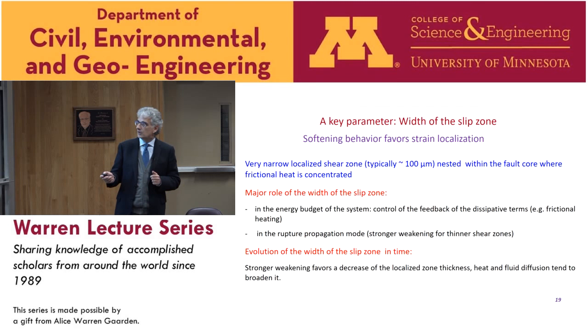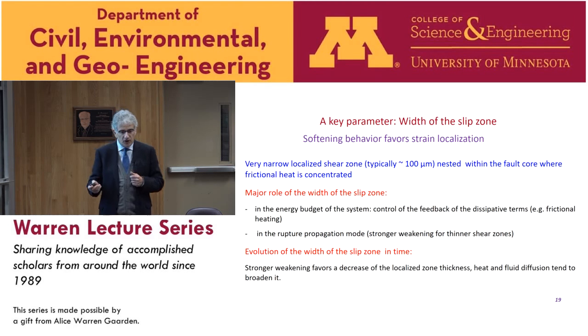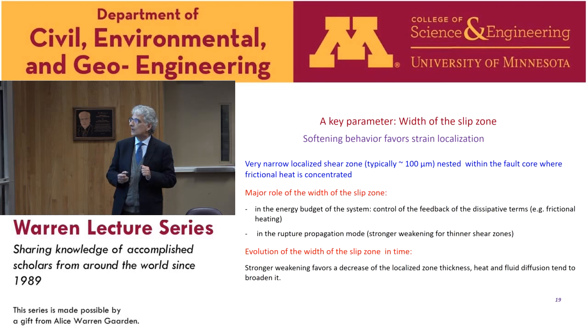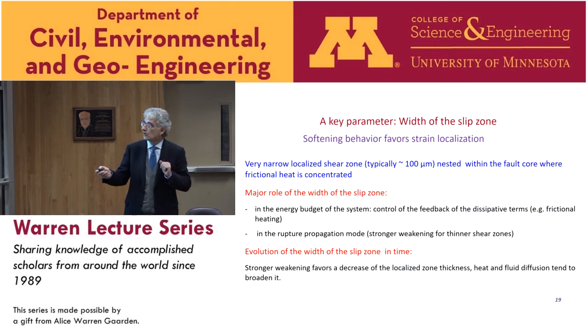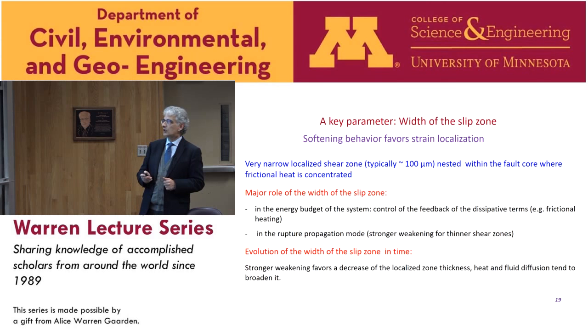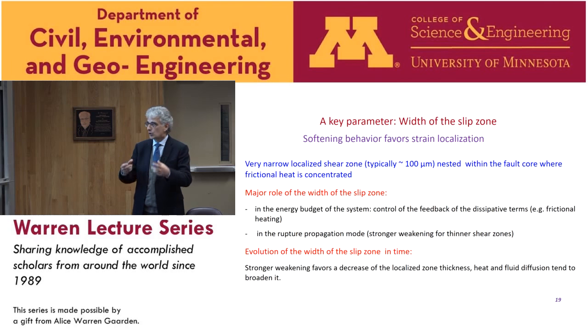We have observed in the field, in the experiments, that the shear is localized typically in zones of a few hundred microns, and it is there that the frictional heat is actually concentrated. So the thickness of the shear zone controls all the dissipative phenomena. So it has a major role in the energy budget of the system, controlling the feedback of the dissipative terms. It also has an important role in the rupture propagation mode, as stronger weakening is expected for thinner shear zones.